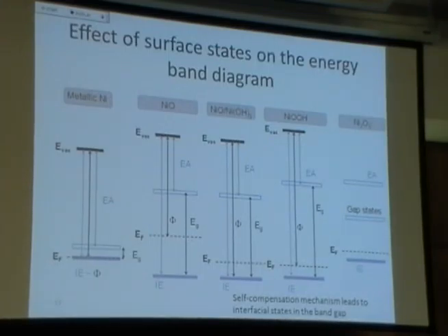Okay, so I've got this messy oxide, and I want it to be thermodynamically selective. I don't want those electrons leaking through. Okay, so again, broken record here. That has to do a lot with what the oxidation state of my nickel is and how that defines my energy band diagram. So, pretty obvious I don't want to start with just pure metallic nickel. I'm going to collect anything, hole or electron, that comes through there. Alright, if I use intrinsic nickel oxide, not very conductive, I'm going to have quite the resistance through that. End of the day, not going to get much current.